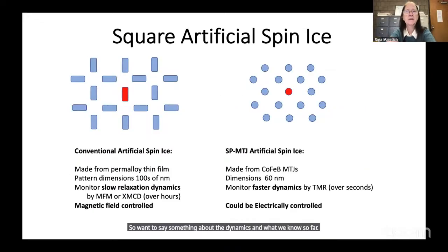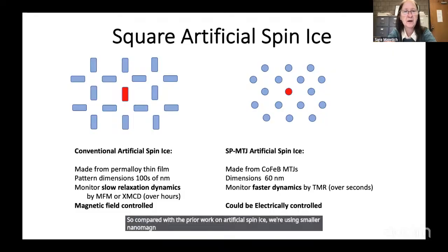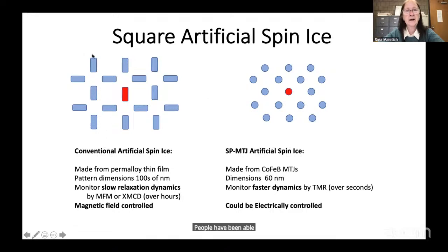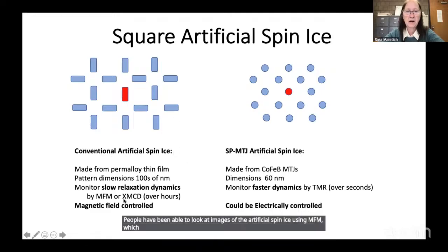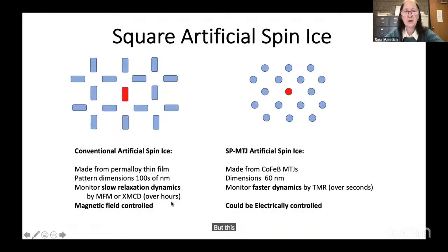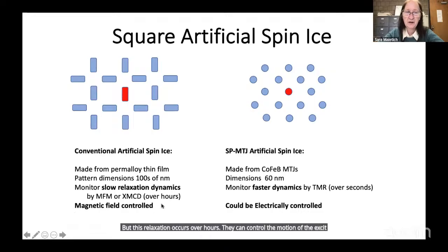Compared with the prior work on artificial spin ice, we're using smaller nanomagnets. Instead of hundreds of nanometers, we've got 60 nanometers. We're making them closer together. People have been able to look at images of the artificial spin ice using MFM, which I showed, but also a lot of work with X-ray magnetic circular dichroism. And beautiful, beautiful images. I'll show you some later. But this relaxation occurs over hours. They can control the motion of the excitations with the magnetic field.